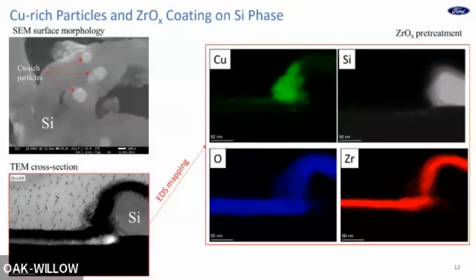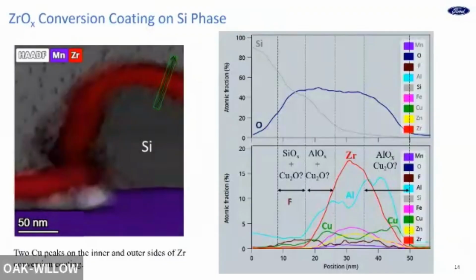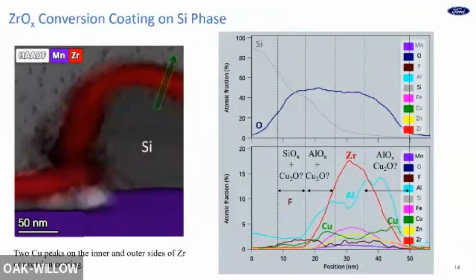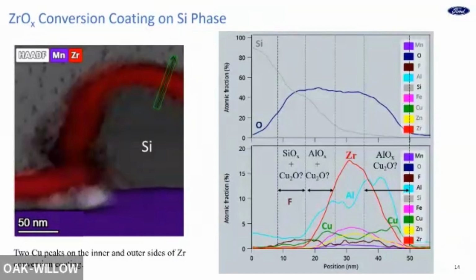The second thing is, in the silicon there's some area without this copper, and does any copper on the silicon surface promote this zirconium formation? So we did a line scan from the silicon phase across the conversion coating. You can see at the beginning the silicon is very high, then you see a zirconium peak, and that's the conversion coating. You do see a copper peak here, and also another peak outside, which was the zirconium conversion coating. Then it really comes to an interesting question: why can the copper deposit on the silicon, and what's the driving force for the zirconium formation on the silicon phase?